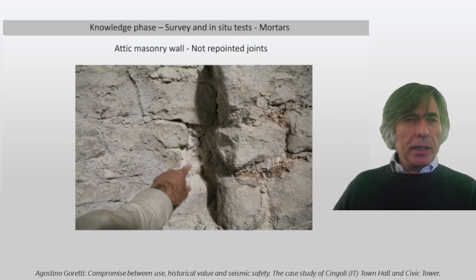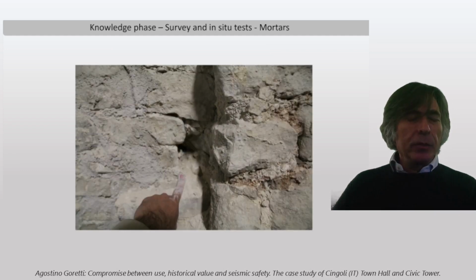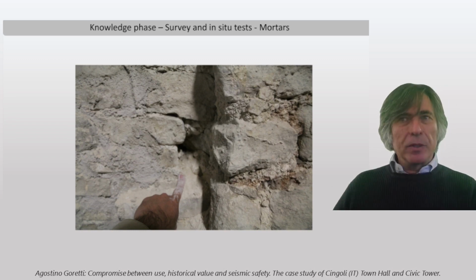I mean, just below the roof, in the council hall room where the theater was, with just your finger you can remove the mortar and make holes in it. So this is clear evidence of the quality of this mortar. Endoscopies were requested in order to understand what's going on through the thickness of this wall. Sometimes these walls are made with two very good external layers, and then inside almost everything, I mean, bad quality mortar, bad quality stones, bad arrangement.